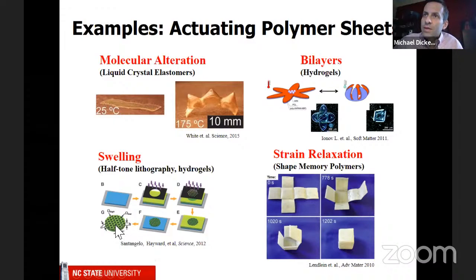So each of these little black spots is a highly cross-linked polymer. So it's a polymer that cannot swell. And depending on where you put these dots, you can get the material to swell in different ways. And so this is a really nice way to control the way a material is going to respond to swelling.